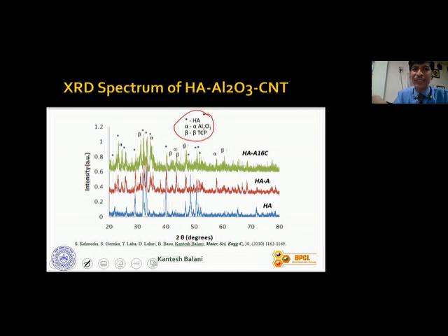I also get crystalline hydroxyapatite. One thing I would like to highlight is that this can be controlled via processing. Especially in elderly people, we require a material which can stay, because the healing process is a little slower. For a younger person, we want the dissolvable phase, which is tricalcium phosphate, to be high in content, because bone is automatically remodeling in younger patients.